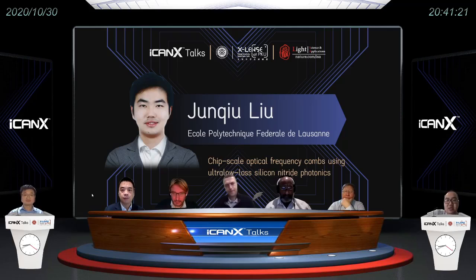If we don't have this stress release pattern, then after 500 nanometers of silicon nitride, there are cracks everywhere. And this reduces the fabrication yield. But with this stress release filler pattern, these trenches modify the stress accumulation directions in the plane. And this can significantly increase the available thickness you can deposit with LPCVD silicon nitride. In our experiment, we have not observed cracks in the silicon nitride film up to 1.2 micron. By zero cracks, I mean literally zero. So the yield is 100%, not 99%. I think we know very well how to manage the stress in the LPCVD silicon nitride film. For other films, usually the stress is compressive because silica usually has a low thermal expansion coefficient. And compressive stress is usually much easier to handle compared with tensile stress.